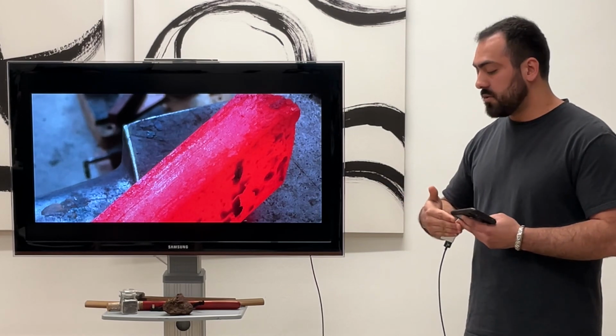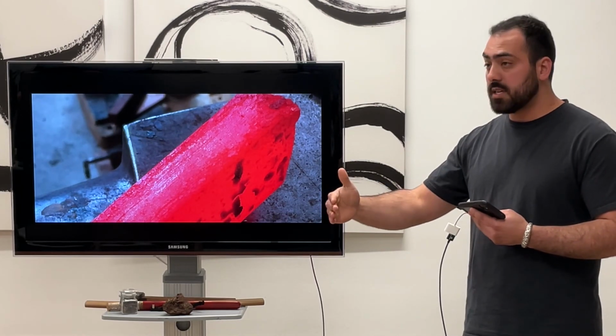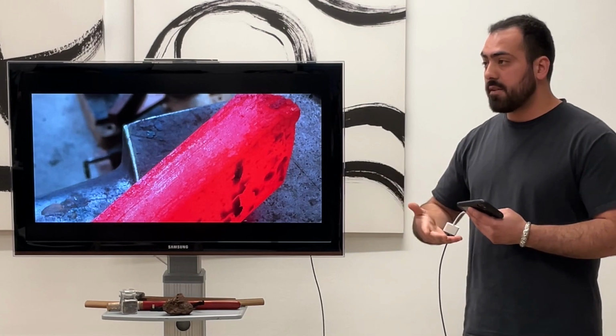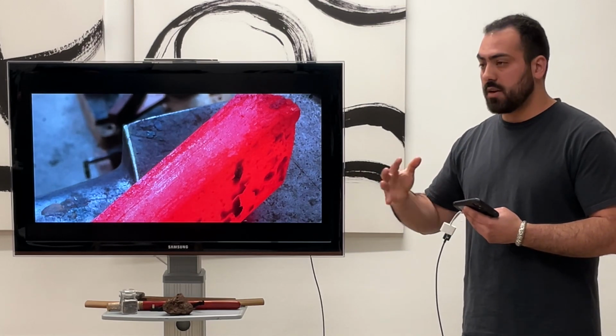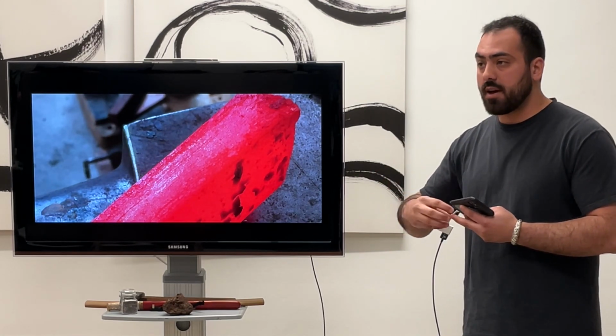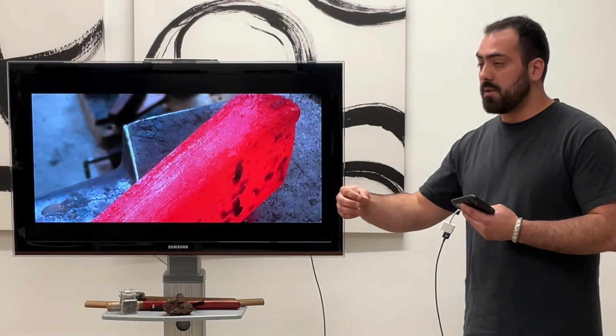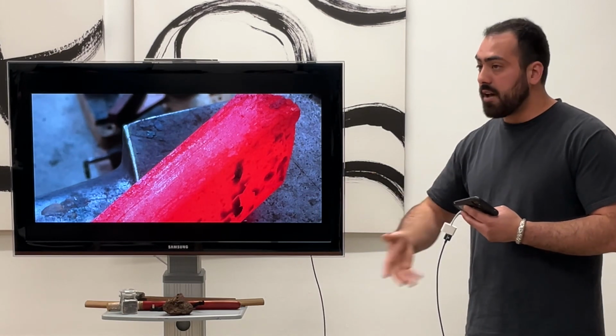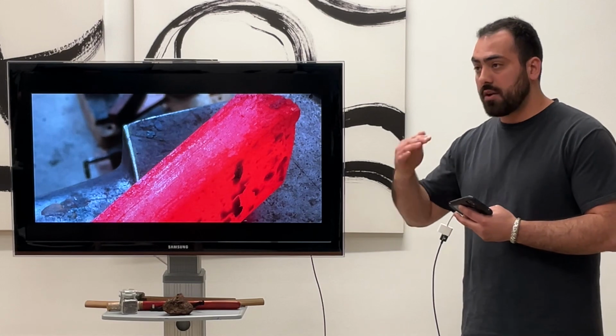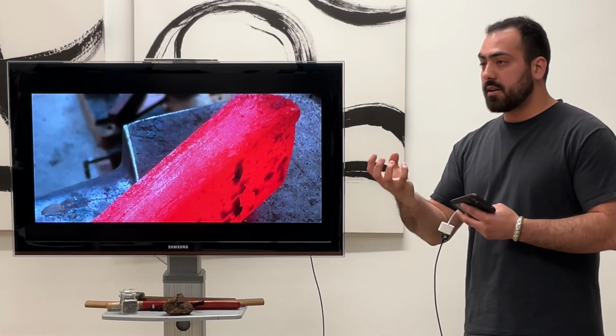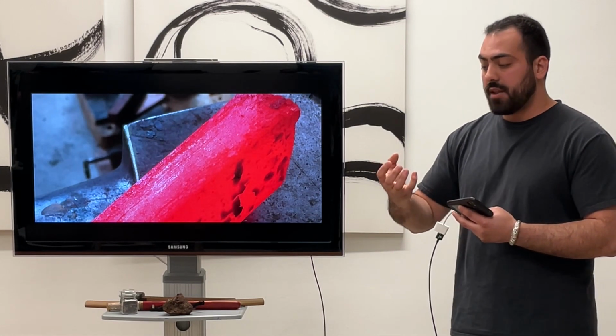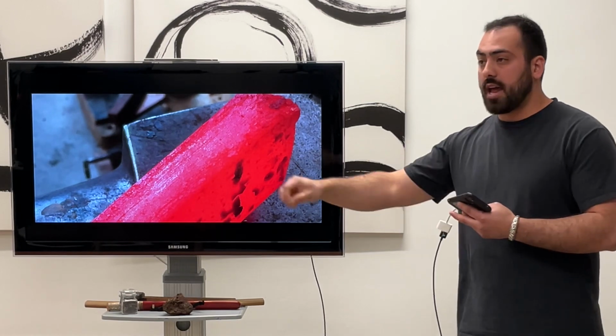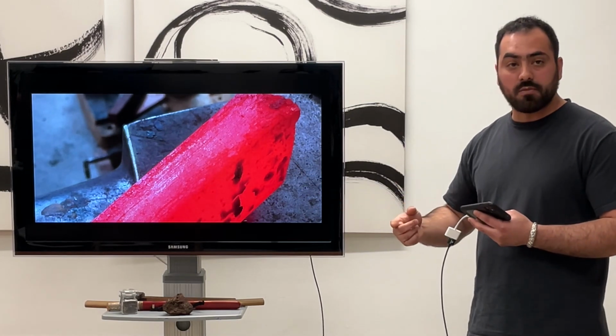I generally tend to forge the billet to maybe 16 inches, fold it, cut it in half. So I've got, you know, an 8-inch piece of metal that's being forged out. I'll forge that out slightly to maybe 12 inches, cut that in half, 6 inches, forge that out. And once I have a block that's big and thick enough, I'll then flip the direction that I'm drawing it out in and then change the orientation of the folding.